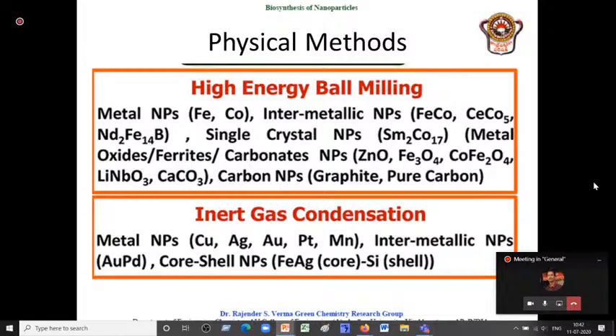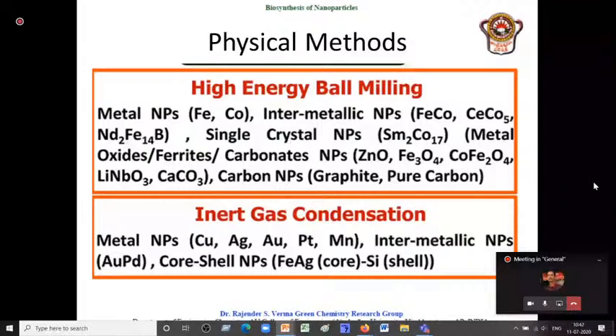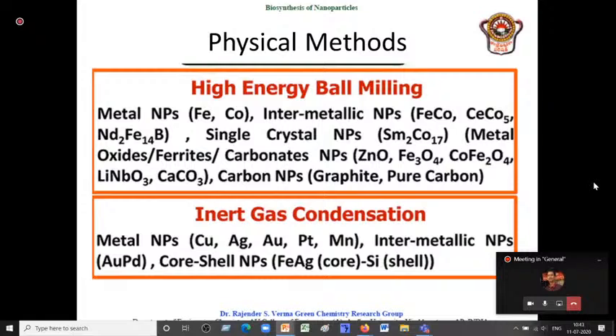So see the kind of nanoparticles that we can prepare using high energy ball milling: metals like iron, cobalt, and alloys like iron-cobalt, cerium-cobalt, neodymium, and then we have single crystal nanoparticles. Then we have metal oxides like zinc oxide, ferrite, cobalt ferrites, and other carbonates, and we have carbon nanoparticles like graphite and pure carbon. We can actually have them by using this high energy ball milling.